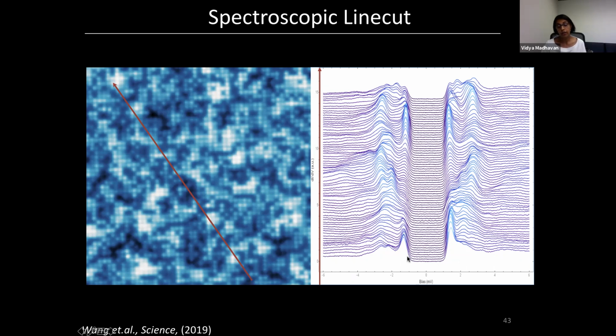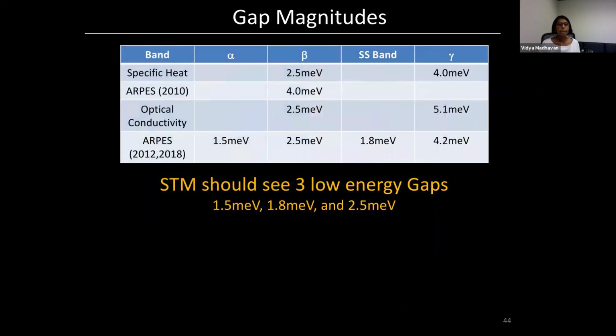There are a couple of things to point out. One is you don't see just one coherence peak, you see 1, 2, 3. And the reason that you see multiple coherence peaks is exactly what I told you before. You have these multiple pockets crossing the Fermi energy. Each of them develops its own gap. And in fact, we can get an idea of what these gaps should be from other measurements, like specific heat, ARPES, and so on. And if you look at all of this data, you realize that STM should be seeing really 3 low energy gaps at these different values. And one of these, which is 1.8 meV, is the superconducting gap in the special surface state that I was talking about, which is, we think, the topological surface state.